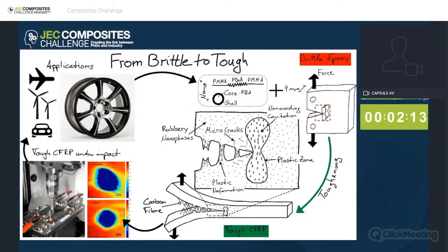We found out that we can, via the curing conditions, adapt the second phase morphology from a nanophase structure to a macrophase structure. However, forming the nanophase structures in our model system took about 2 weeks. It was quite difficult. So this is not a real approach for a manufacturing process. So we adapted our curing cycle, went on to the matrix level, and tested our fracture toughness for that. What we found is already an enhancement of the interlaminar energy release rate of about 7-fold, meaning we were already able to drastically enhance our fracture toughness.